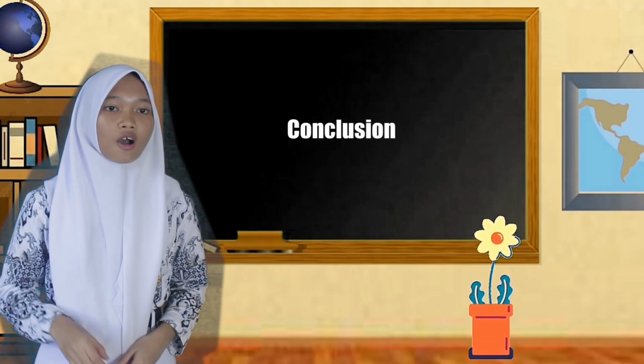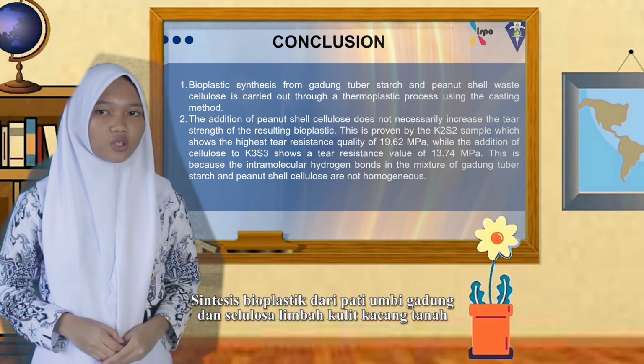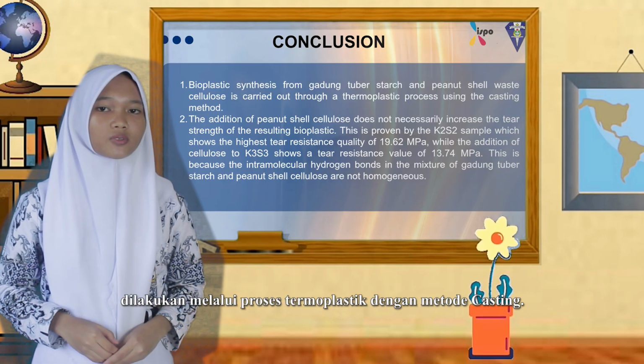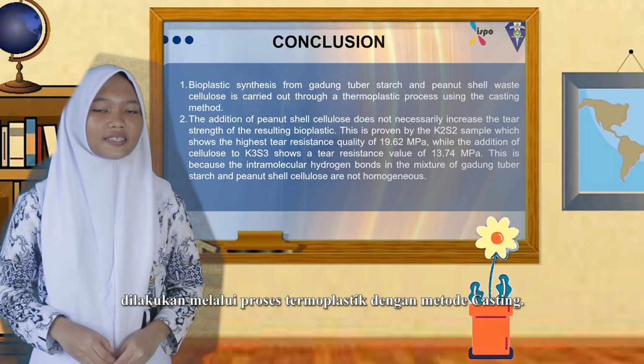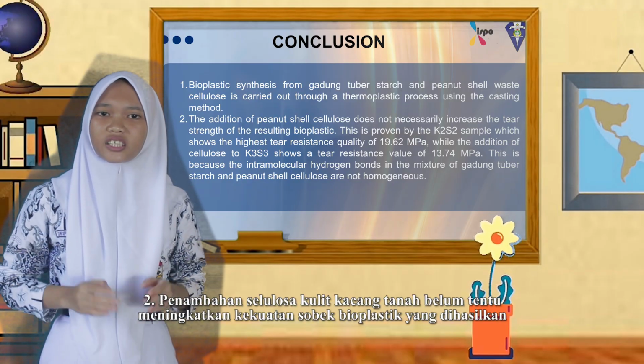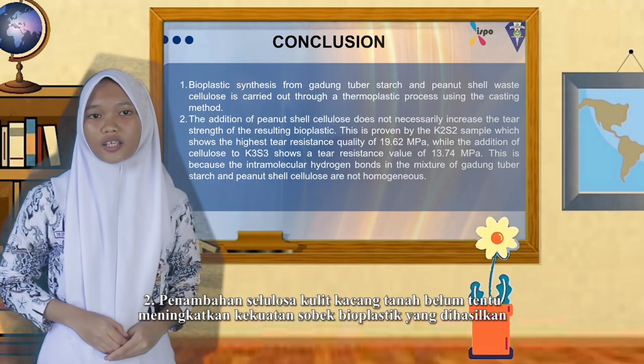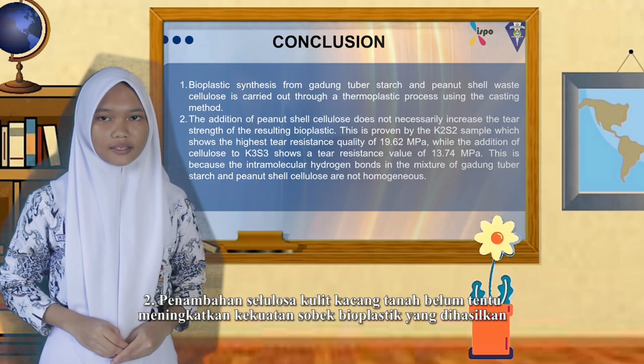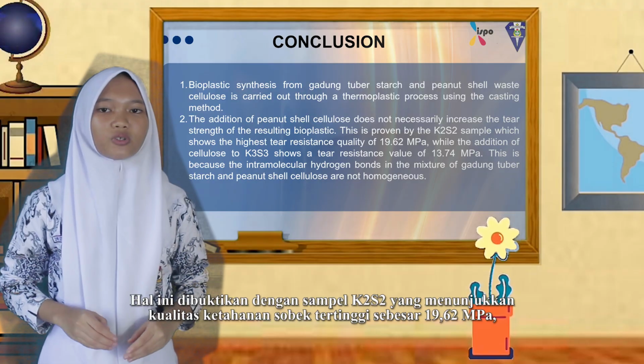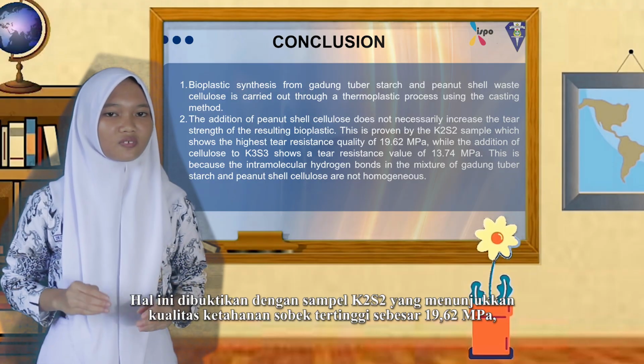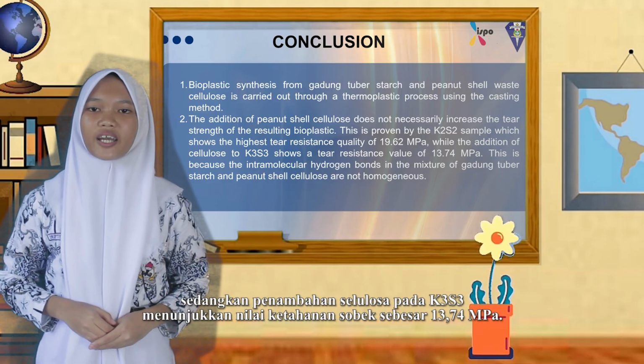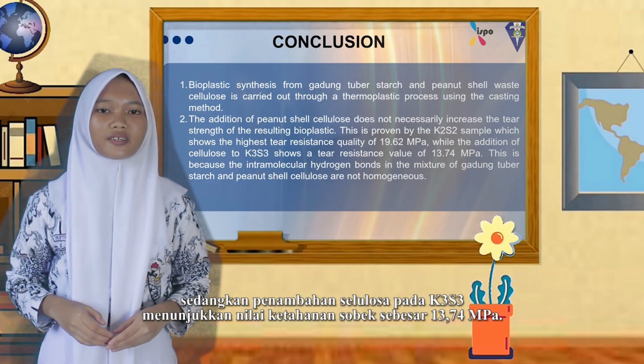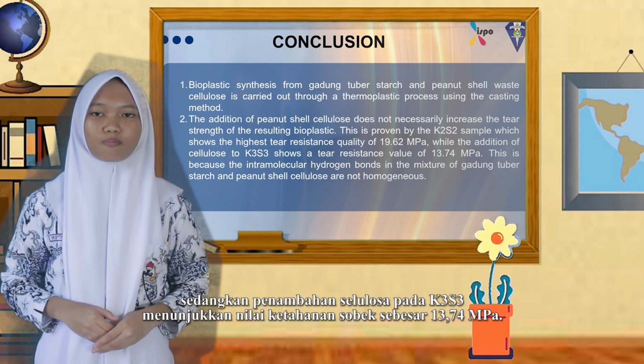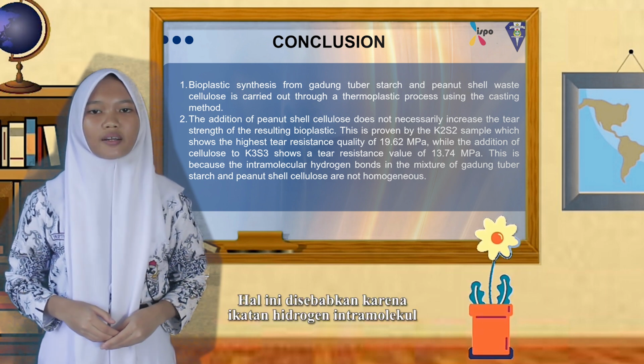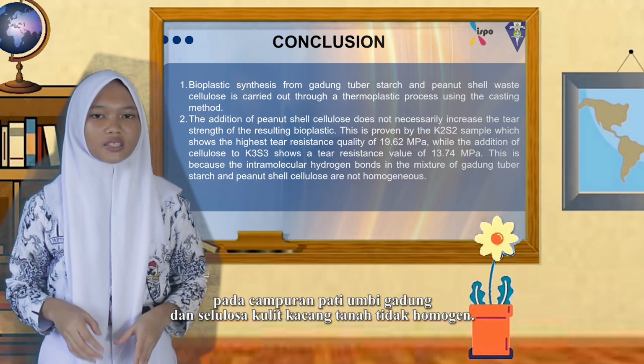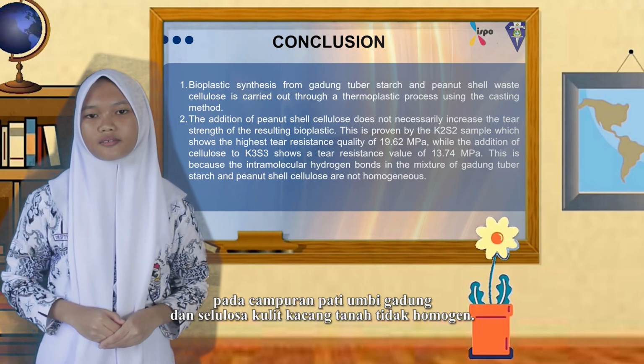The conclusions of our research are: first, bioplastic synthesized from gadung tuber starch and peanut cellulose is carried out through a thermoplastic process using the casting method. Second, the addition of peanut cellulose does not necessarily increase the tear strength of the resulting bioplastic. This is proven by the K2S2 sample, which shows the highest tear resistance of 19.62 MPa, while the addition of cellulose in K3S3 shows a tear resistance value of 13.74 MPa. This is because the intramolecular hydrogen bonds in the mixture of gadung tuber starch and peanut cellulose are not homogeneous.